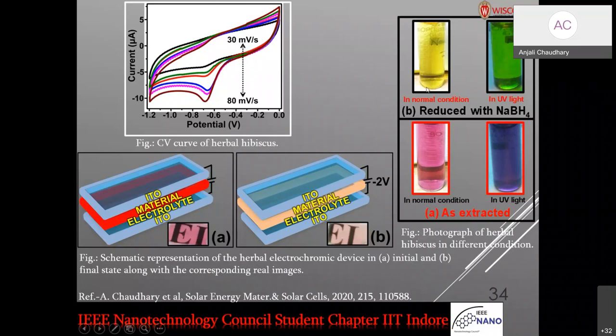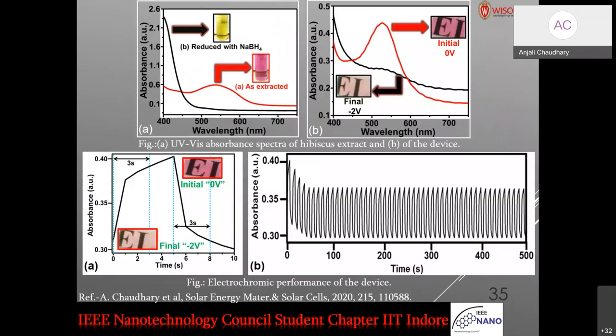So the next thing is to reduce it not chemically, but by putting it in a device form and then reducing it electrically by applying a bias. Under UV light, it also changes its color from magenta to some other color, yellow to green. When we made an electrochromic device using this, we put a layer of hibiscus over one ITO, and in between there is a gel electrolyte. We mostly use gel electrolyte in making our devices because it cannot flow out of the device. It is easily controllable as compared to the ionic one.